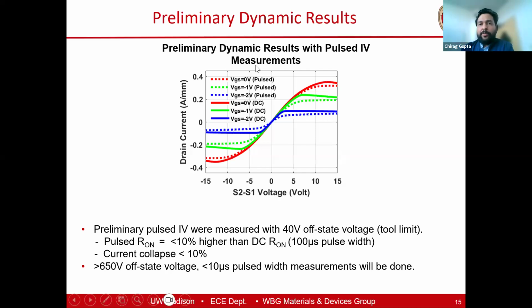We also started doing some pulsed and preliminary dynamic results. Due to the limitation of the tool, we were only able to apply up to 40 volts. So what you are seeing here is the off-state stress, or the quiescent point, was set up to 40 volts, and the pulse width limitation also came from the instrument. Currently, we are in the process of upgrading our instrument so that we can go up to 3 kilovolt in off-state stress and basically get some sense of dynamic performance from these devices.